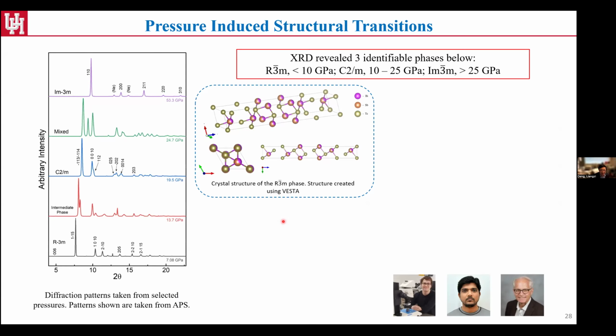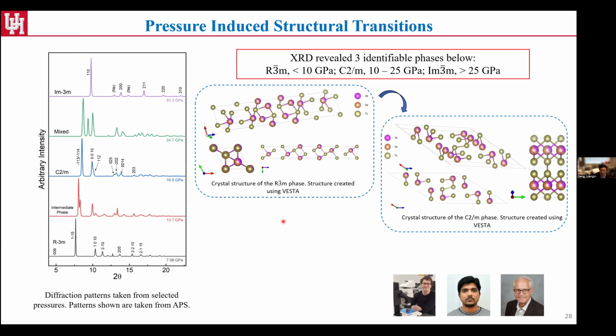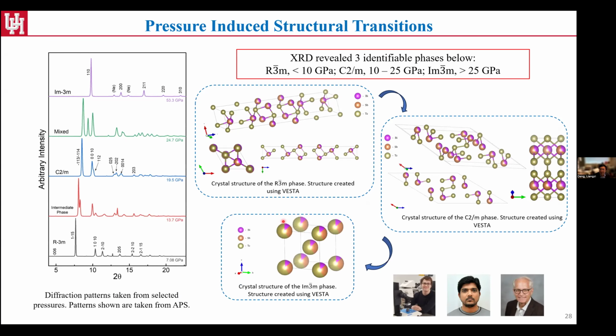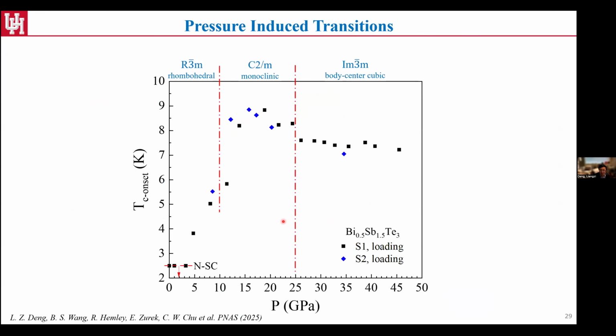So below 10 GPa is rhombohedral, between 10 and 25 GPa is monoclinic, and above 25 GPa it turns into cubic. So these 3 phases and 2 phase transition critical pressures match really nicely with the TCP we mapped out. That can very well explain why we see the jump here and also the small drop when we go to even higher pressure. But the question remains, what's really going on when it changes from the non-superconducting phase to the superconducting phase, right? That's within the same structure, right?